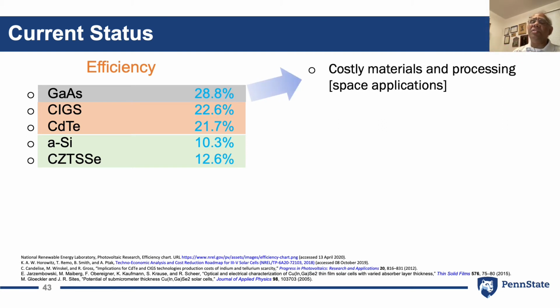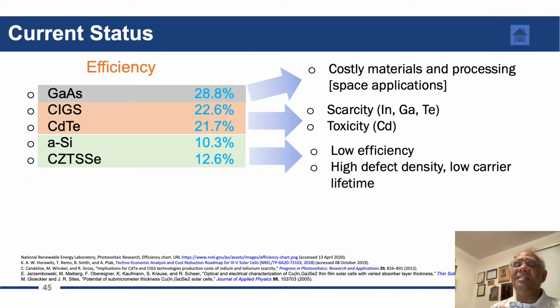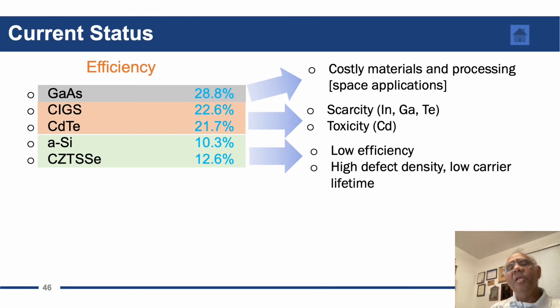Now, gallium arsenide is too expensive for use on Earth. CIGS has three scarce materials: indium, gallium, and tellurium. Cadmium telluride has cadmium that is toxic. Amorphous silicon and CZTSSe have low efficiencies due to high defect densities and low carrier lifetimes. So we must find a way to increase the efficiency and still use a small amount of semiconductor material. That is, we must remain in the thin film format for microgenerators.